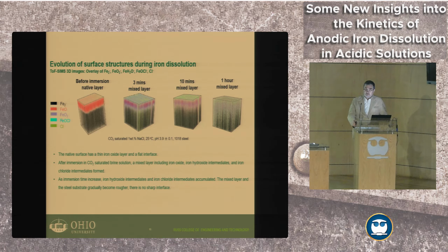If you're a good scientist, you always have to worry about it like you do. So how do you distinguish it? Let's assume that one of those 2 compounds is a hydroxide and another one is a sulfate. It doesn't matter. But they happen at the same rate, so when you do that EIS, it's always the same. So you don't even know there's 2. But then if you do it at different pHs, but at the same sulfate concentration, they will separate from each other. Or if you do it at the same pH, but different sulfate concentrations, they will separate from each other. Or chloride, it doesn't matter, I just used an example of 2 pathways.